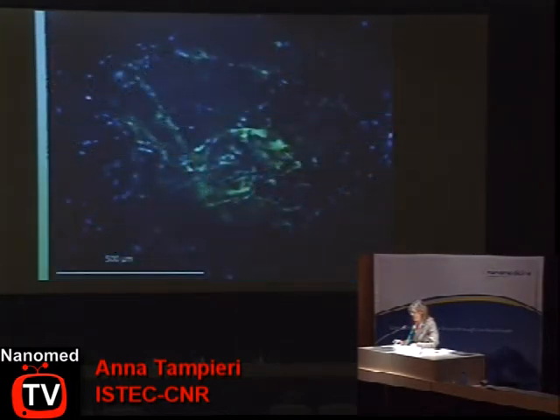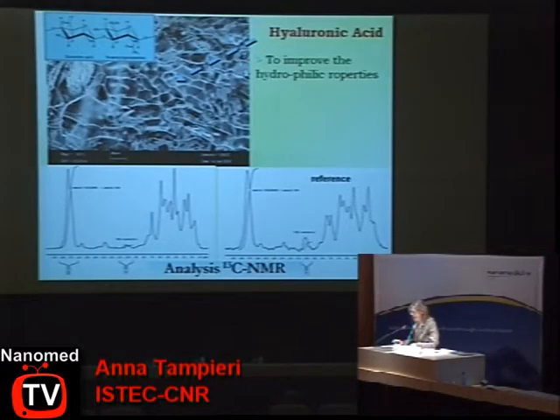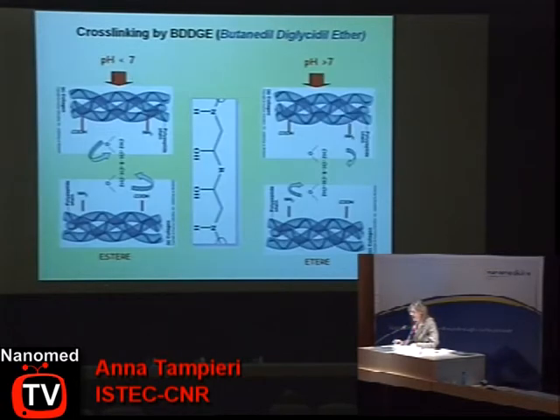Here we have an image showing, in blue, the nuclei of the cell, and in green, the actin filaments. Then we also had hyaluronic acid in the cartilaginous layer to better mimic the upper layer of the scaffold, and a cross-linking agent to stabilize the overall composite in order to control the degradation rate and make it as similar as possible to the remodeling kinetic.